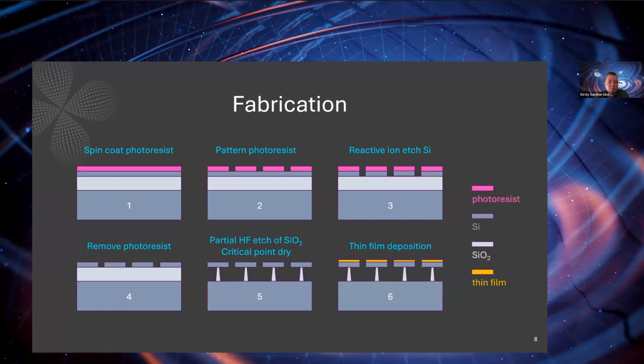And then the next step is to create the pillar on which the microdisc sits. We do this using hydrofluoric acid, which selectively eats away at the silicon dioxide, but leaves the silicon untouched. And then we critical point dry the sample so that the discs don't collapse, but remain standing nice and free. And after this step, that's when we can do the thin film deposition and put the material on that we want to test.